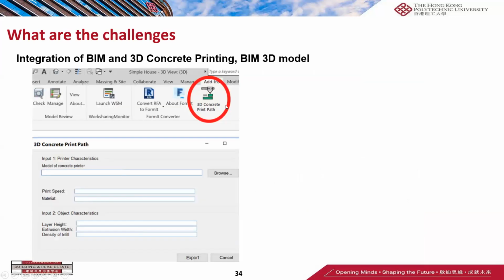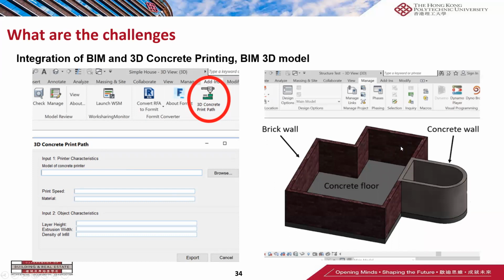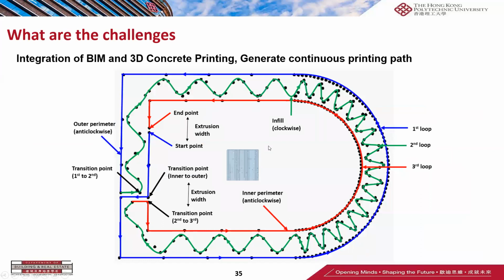So this is the developed plugin in Revit for the concrete printing path generation. We know that in Revit, we can design the BIM model, just like this. We can have the brick wall, the concrete floor, and also the concrete wall. Then in the user interface of the 3D concrete printing plugin, we can define which kind of material we want to print. For example, if we want to print a concrete wall, then you can just input the concrete wall here. At the same time, we can input the print speed, the layer height, extrusion width, density of infill, and so on and so forth, all these parameters which are required for the concrete printing process. Then this plugin can automatically detect the concrete wall in Revit, and then generate this kind of continuous printing path for the concrete printing.